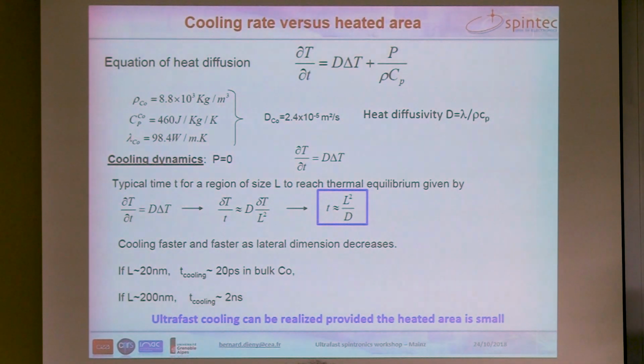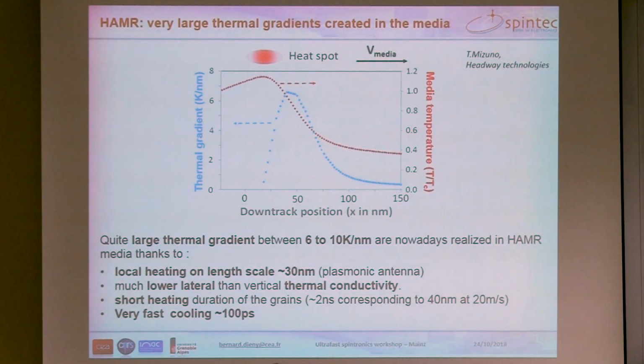And this is why we use plasmonic antenna in this technology, because not only we want to heat a region comparable to the bit size, but also we want to cool very fast. So thanks to this, it's possible to create a very strong gradient in the media. And these are actually simulations performed at Headway Technology using a finite element solver simulation of the profile of temperature underneath the heat spot. So you can imagine that the media is moving underneath the heating spot here, so the plasmonic antenna, at a velocity of 20 meters per second.